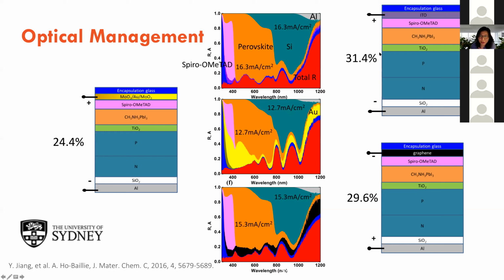And if you move to the right-hand side, you can see that the ITO is performing better. So there's not much absorption there. You can hardly see anything. You can see a little bit. And a lot of light gets through to the perovskite cell. So it's managed to produce 16 milliamps per square centimeter, and so is the silicon cell.